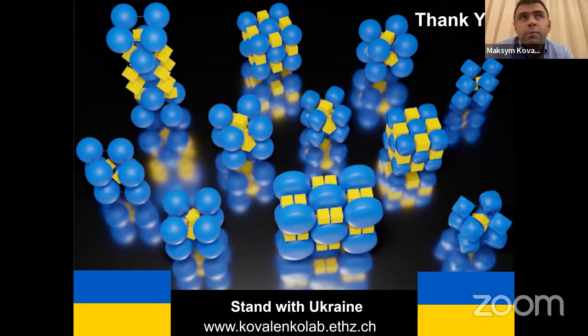For instance, I didn't show anything on light-emitting diodes with perovskites, because I believe that they are inherently unstable because of the electrochemical activity of lead 2+. That's where cadmium-based QDs have higher potential. But for the applications where you use down conversion, such as LCD displays, I think perovskites will be commercialized in the next couple of years as a television display emitter.